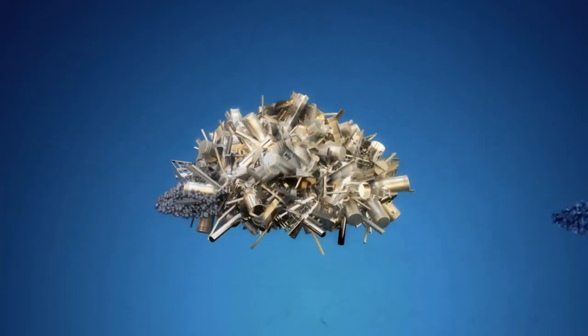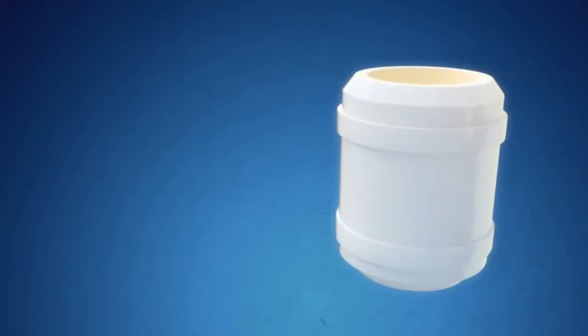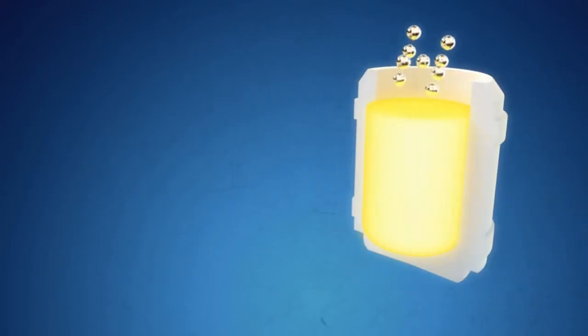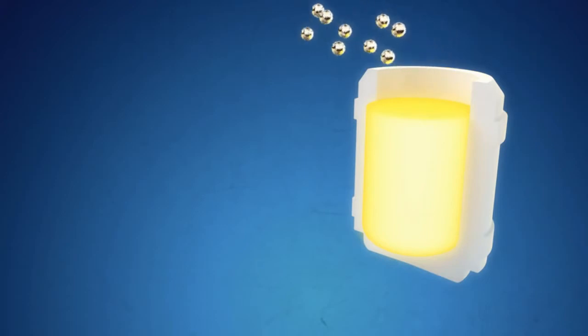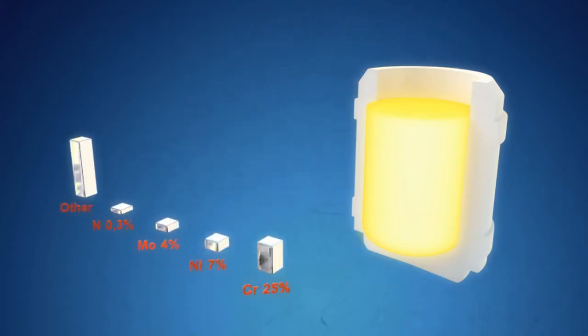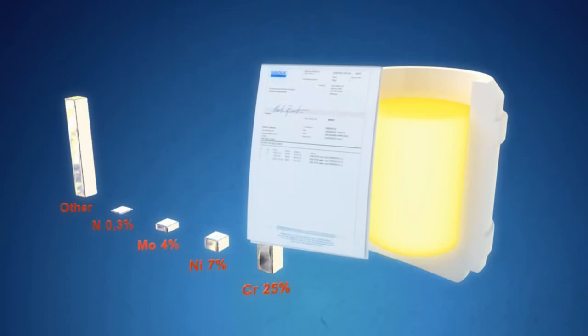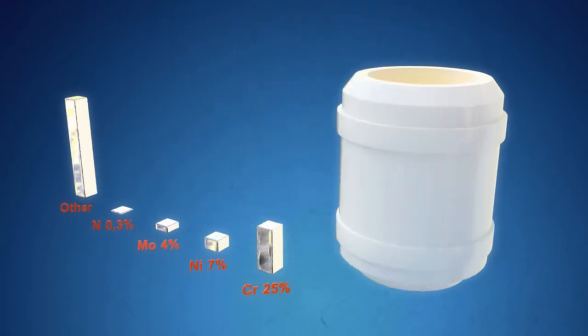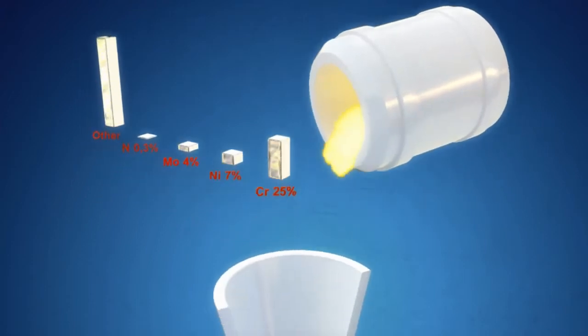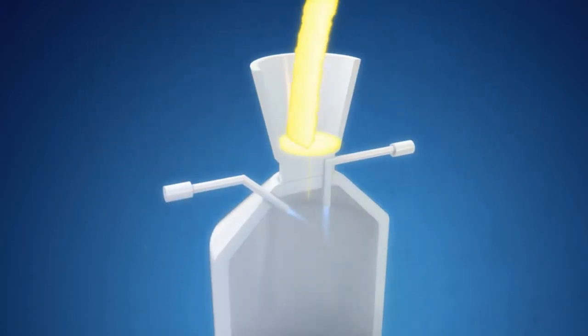The manufacturing of metal powder for the HIP process is based on controlled quality scrap and alloying materials. Melting takes place in an induction furnace. The chemical composition of the melt is closely monitored throughout the process and adjusted to meet Sandvik requirements and international standards. The powder is produced by blowing inert gas through the melt, which solidifies into small spherical metal droplets.